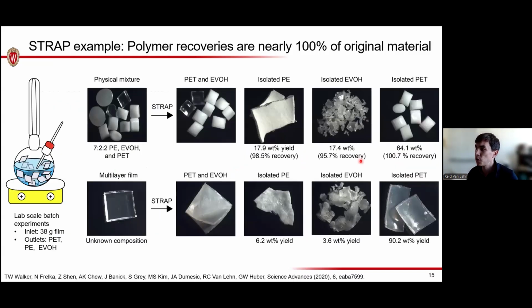Okay, so we can do this with a whole bunch of different systems. Here's an example of what it looks like. We just took a physical mixture of these different polymers. We did STRAP, we chose solvents, we dissolved and reprecipitated. You can see we get out the isolated polymer components. PET is the last thing we try to dissolve, so we never dissolve it, and that's why it still comes out as these pellets. Once we've done the physical mixture, we take an actual multi-layer film. This is a commercial product provided by our collaborators. We do the same process, we get the same yields. We've done a lot of characterization to show that the polymers are coming out in a chemically pure form.